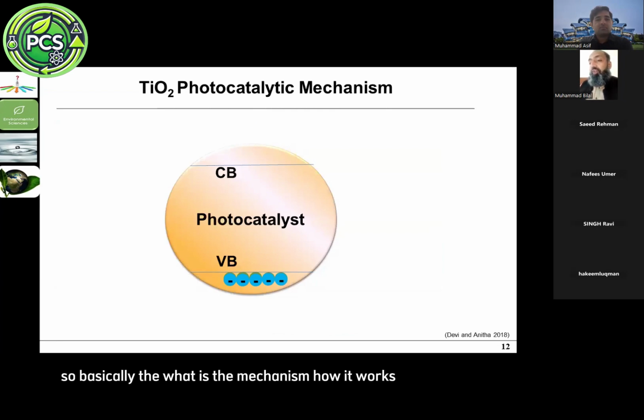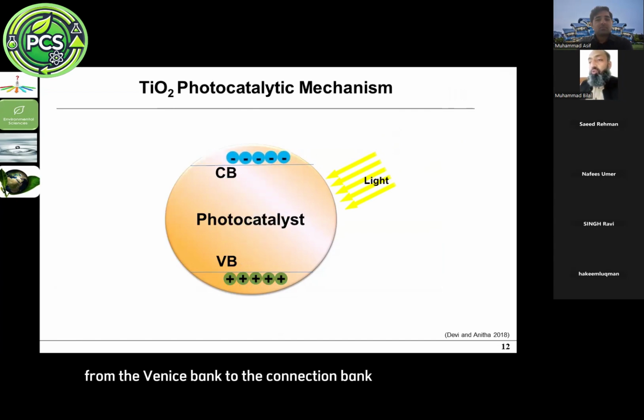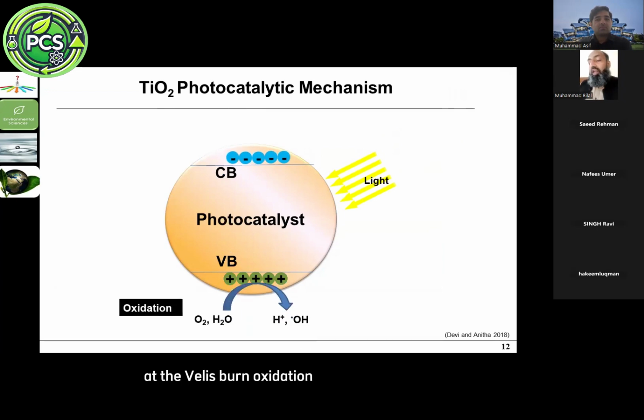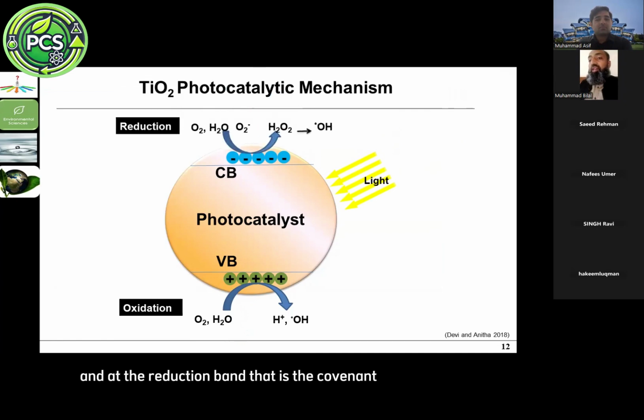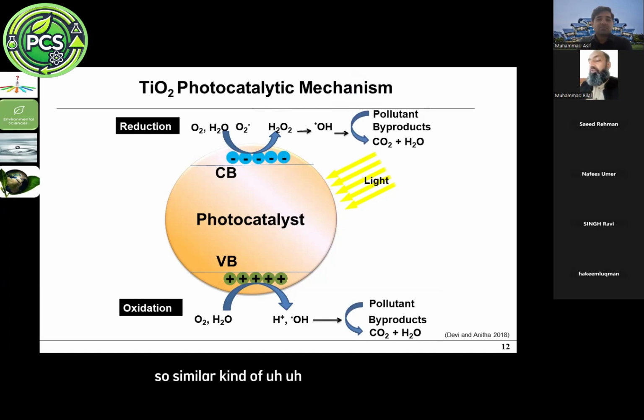So basically, what is the mechanism, how does it work? When visible light falls on the catalyst, electrons are generated from the valence band to the conduction band, and holes are generated behind. At the valence band, the oxidation reaction proceeds with the generation of hydroxyl radicals, and at the conduction band a reduction process occurs, with H2O2 production and hydroxyl radicals, that is, the reactive oxygen species, generated. These reactive oxygen species attack the organic contaminant, in this case reactive black 5, and degrade it into carbon dioxide and water. So similar end products are produced at both the valence band and conduction band.